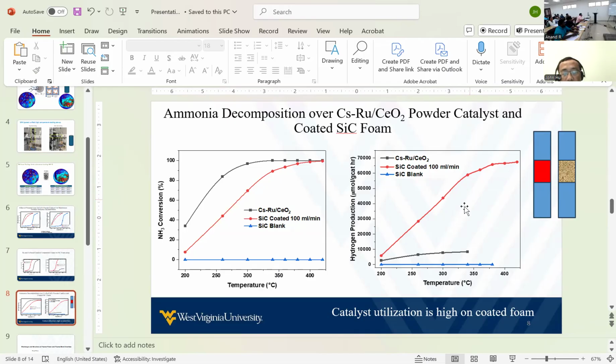I'm not sure I illustrated. So basically, if you correct the productivity based on active ingredient, because here's 100% active ingredient, all right? On the right-hand side, the powder or active ingredient is only a fraction because the majority volume is non-reactive silicon carbide. So if you do the correction and then calculate the production, oh, this form is much better. So we win the game.